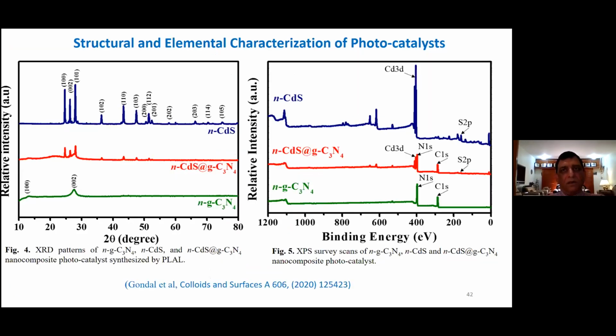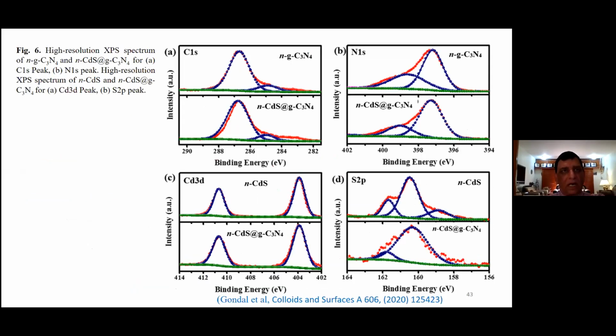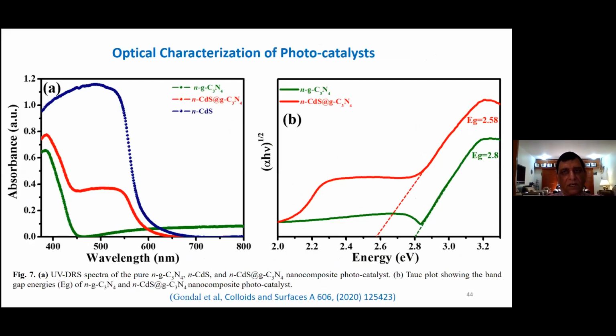And here we do the XRD to test whether we have CdS and graphitic carbon nitride, and you can see all these peaks. When we have this nano composite on the right hand side with XPS, we have proved that carbon is there, nitrogen is there, cadmium is there. So all this we can verify through our XPS machine. These are the high resolution XPS, and we can also identify the atomic level. You can see S state, P state, D state, all these states, we can identify them.